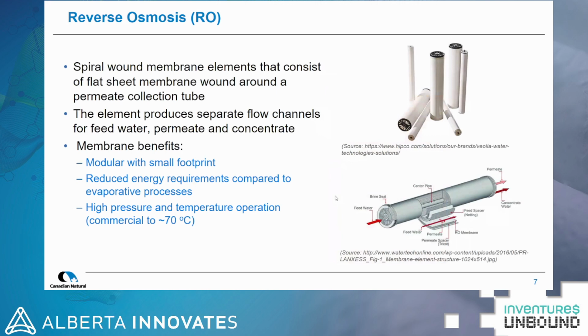This design offers a lot of benefits. It offers a very small footprint. You can get a lot of filtration area in a small footprint. It's lower energy versus other technologies that do similar things. So when you compare it to evaporators for TDS removal, this is a less energy intensive process. It's suitable for relatively high pressure and high temperature operation, but commercially, it's limited to 70 degrees C.